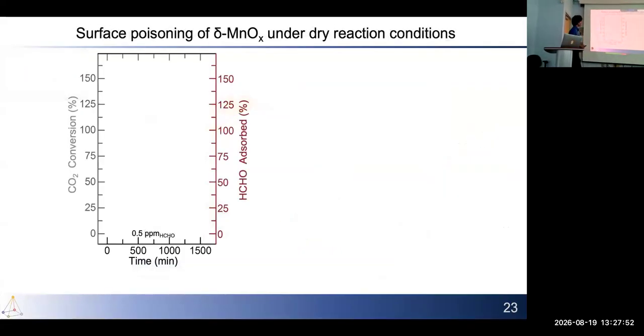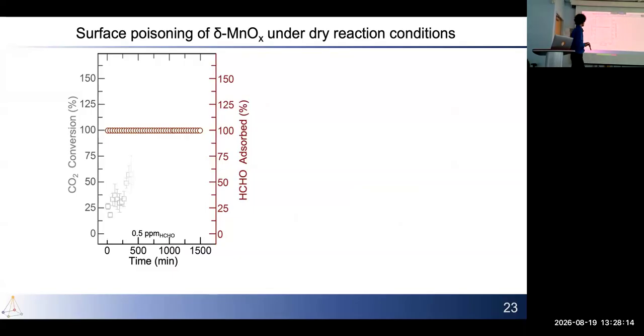So here's a typical plot of what we'd get from one of these experiments. Here you have how much CO2 is being converted, how much formaldehyde is being adsorbed as a function of time. So under normal dry conditions, what we see is that generally manganese oxide behaves like a sponge. It adsorbs all the formaldehyde, but only roughly produces about 40% of CO2. So the rest is just sitting on the surface and then building up, and it will eventually die.